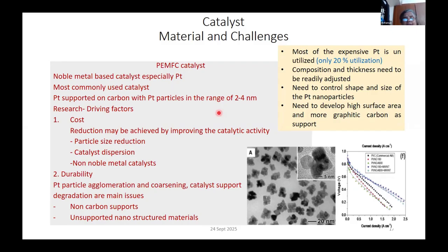Other than that, there is also research on non-noble metal based catalysts. However, these are not yet commercialized, because, like I said, the best catalyst is platinum. So most of the research is on platinum. The second thing you can do is improve the durability. If your catalyst works for a longer time, you can also reduce the cost of the stack. Instead of 40,000 hours, if you are able to run the cell for 100,000 hours or so, your cost also reduces. Here you will have to study agglomeration, coarsening, catalyst support degradation, and non-carbon supports. These are the main things that you have to study.